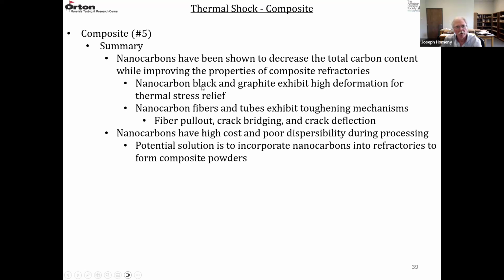Nano carbon black has been used. Nano graphite has been used. They all tend to improve the strain of failure, so they have high deformation for thermal stress relief. Nanocarbon fibers and tubes have also been used, and they enhance some of the toughening mechanisms like fiber pullout, crack bridging, crack deflection. The problem with nanocarbons, they have high cost. If you're trying to make a refractory product that's low cost, that's going to be a big issue. And they're hard to process. They're hard to disperse because of the fine particle size and high surface area.